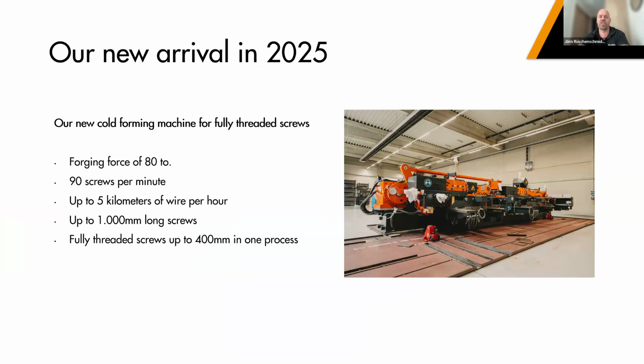It has a forging pressure of up to 80 tons. It does 90 screws per minute, and every hour we run up to 5 kilometers of wire through this. We can do up to 1,000 millimeter long, partially threaded, or 400 fully threaded. This is now shown in a little video. Again, excuse the stuttering, but this is just caused by the bandwidth maybe.